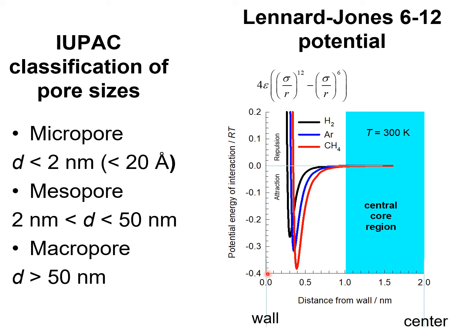We note that at the distance of 1 nanometer from the pore wall, the potential energies of interaction are close to zero. Therefore, for mesopores with effective pore sizes larger than 2 nanometers, there is a central core region in which molecule-molecule collisions are dominant and molecule-wall interactions are of negligible importance.